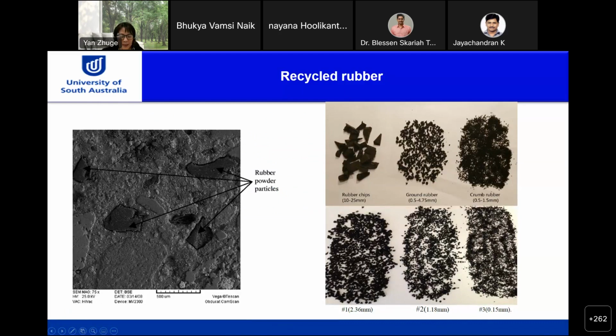So before making crumb rubber concrete, we researched the rubber size effect, because we got all different sizes from the manufacturers. They could have very large sizes as rubber chips. The size can be up to 10 to 25 mm. They could be used to replace the coarse aggregate.